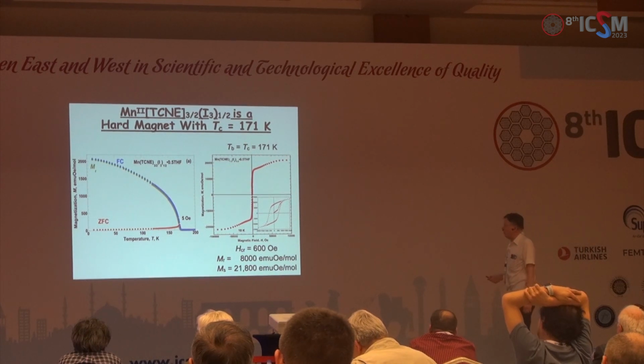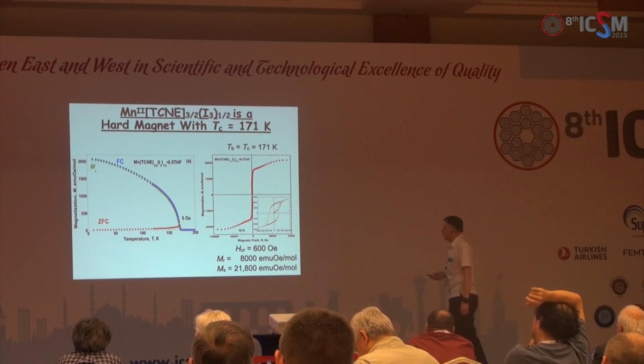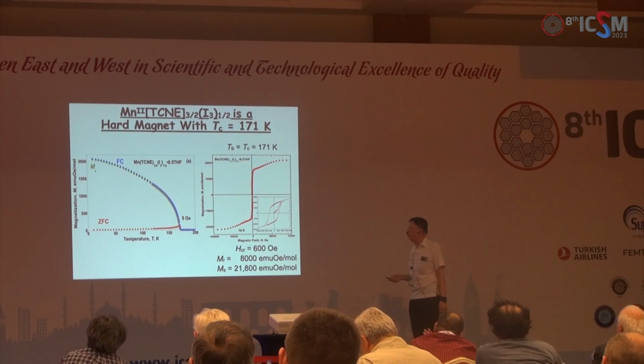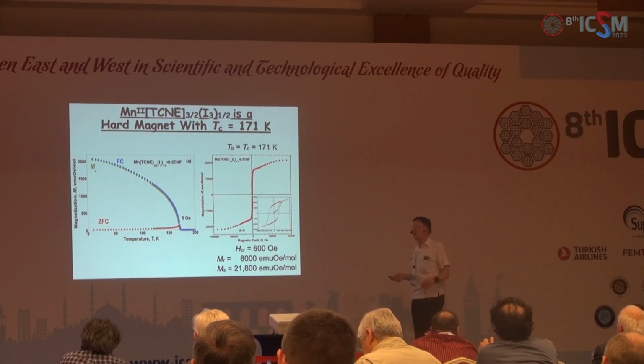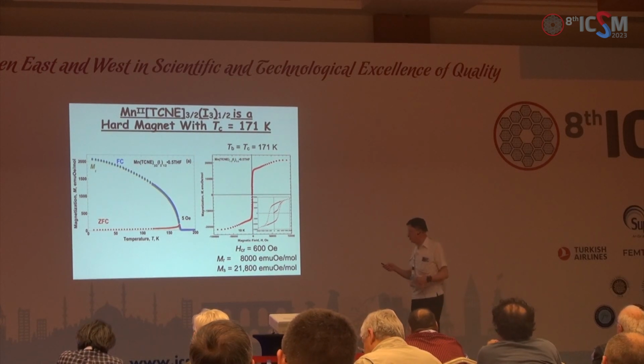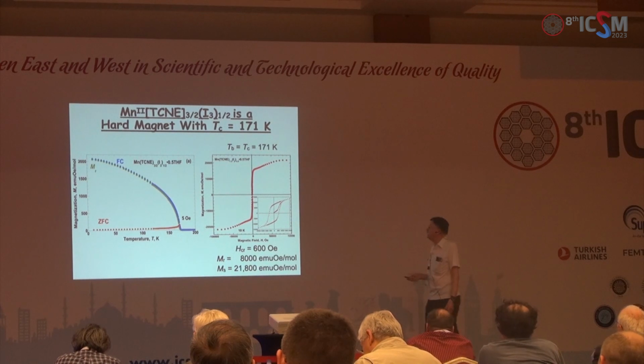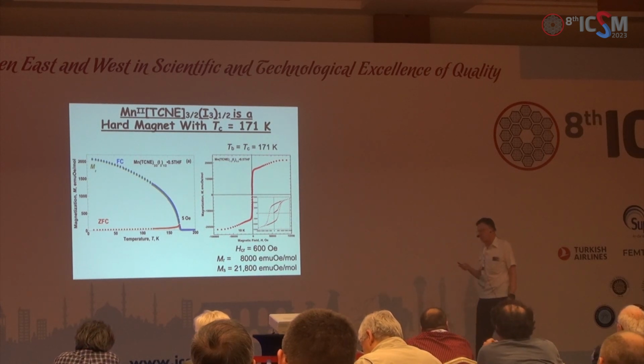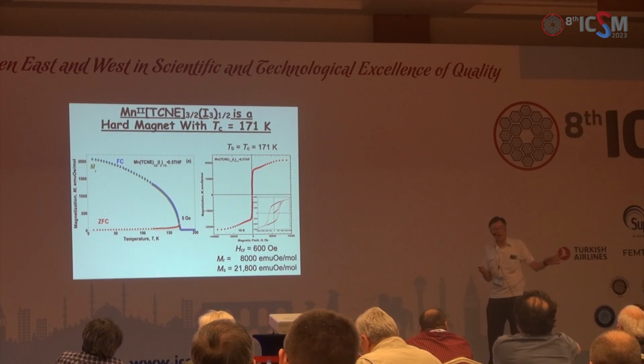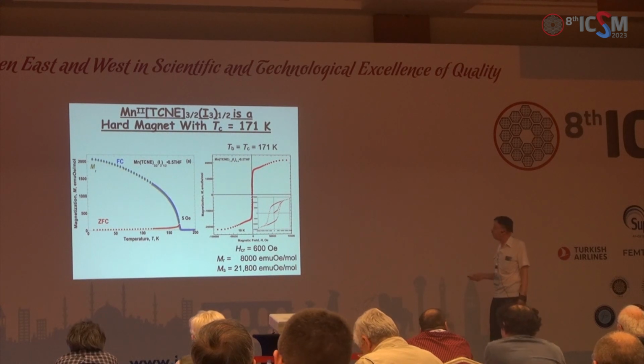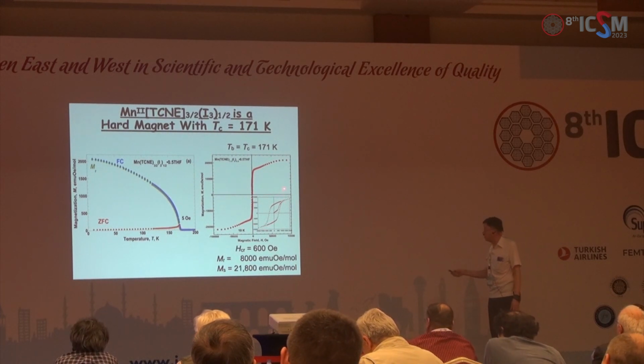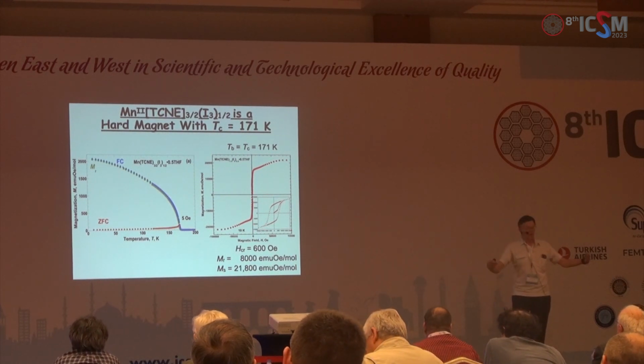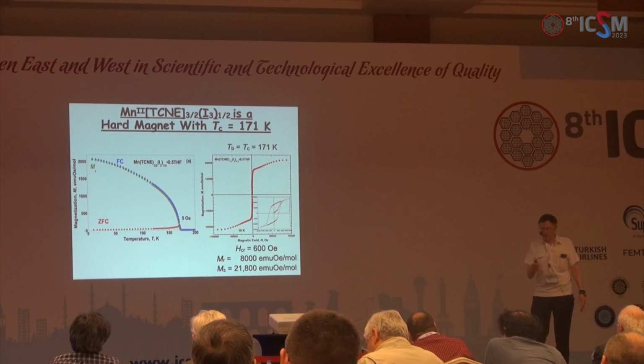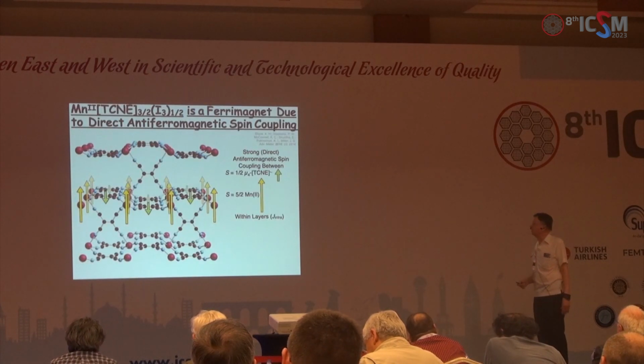The magnetic ordering temperature, determined from the bifurcation of the field-cooled and zero-field-cooled curves, as well as the remnant magnetization going to zero, is basically 171 Kelvin, over 100 degrees higher than the previous compound. And here are the hysteresis loops you'd expect for a magnetically ordered ferrimagnet.